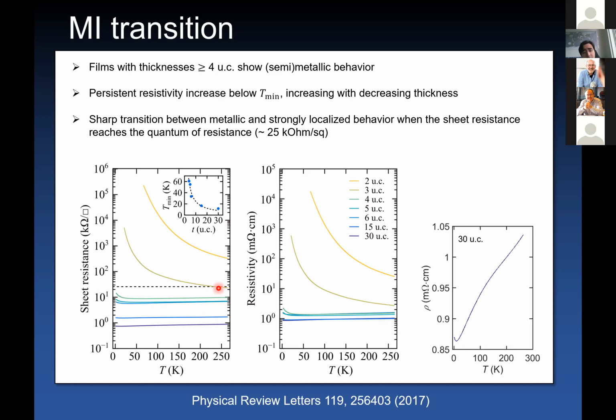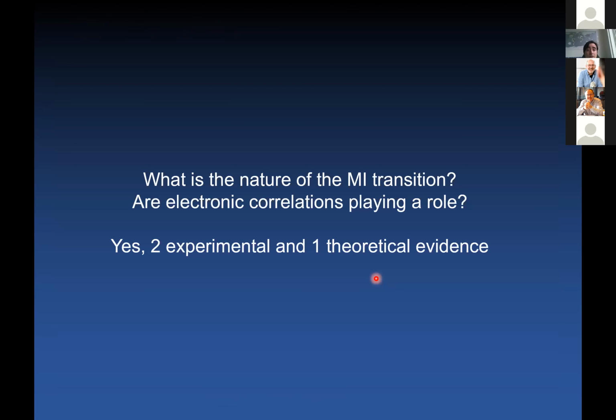Already in the high temperature range, the sheet resistance of the system is of the order of the quantum of resistance, 25 kilo-ohm. So already in a strong localization sense, it is expected that these films will undergo a localization of the wave function. So the question is, is there any role played by electronic correlations in this metal-insulator transition? And I will argue that electronic correlations are indeed important, and I will show you one theoretical and 2 experimental evidences for this.